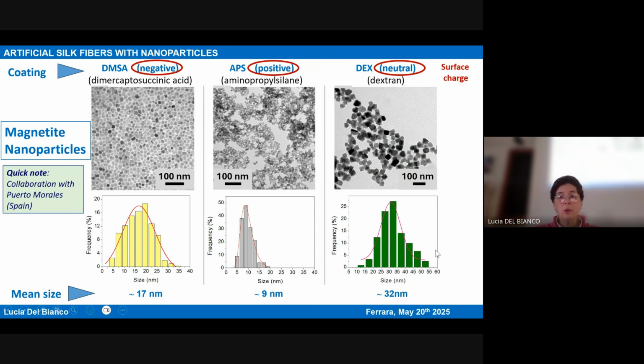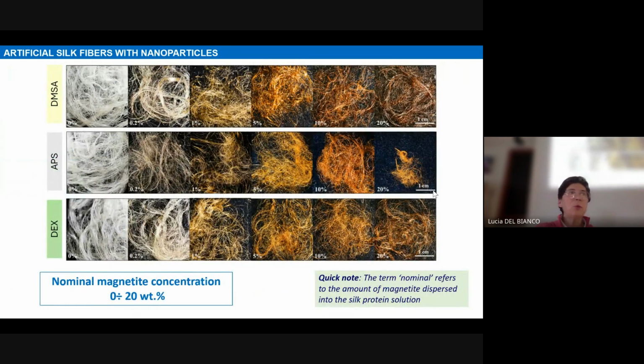Of course, these are distributions of the size of the nanoparticles, and the mean size was different, 17 nanometer, less than 10, and these were quite big, 32 nanometer. And using this type of nanoparticles, actually, our Sweden colleagues succeeded in doing something that they were not able to do using naked nanoparticles, which means really producing meters and meters of continuous fibers. And they also changed the nominal magnetite concentration in the fibers. So starting from the pure fiber, which is white, and then increasing the magnetite concentration, you see that the color changes and goes towards a dark brown.